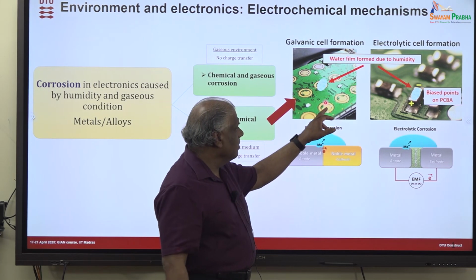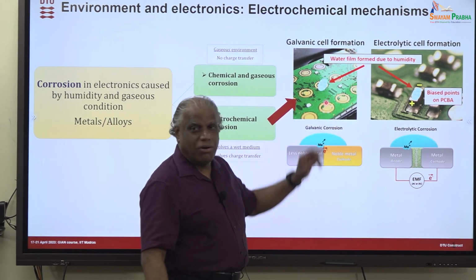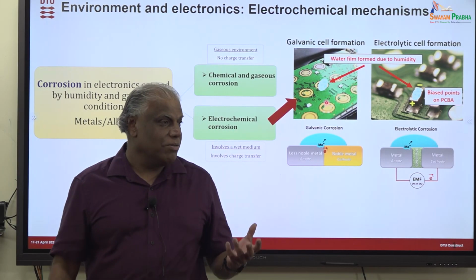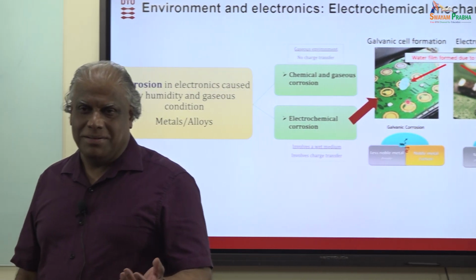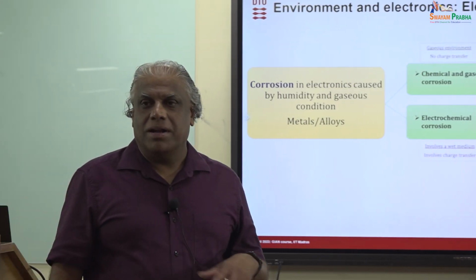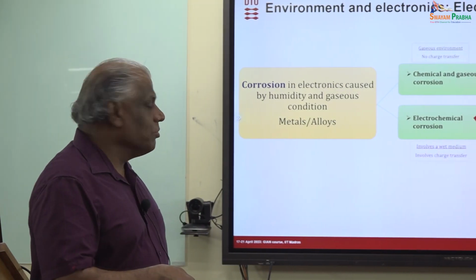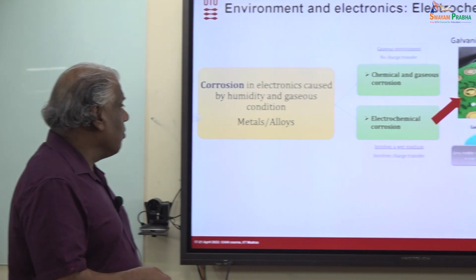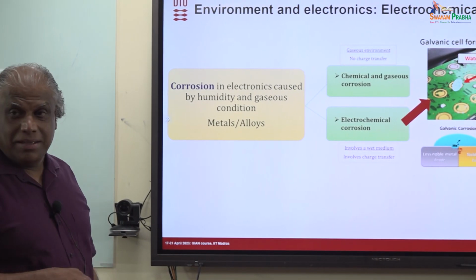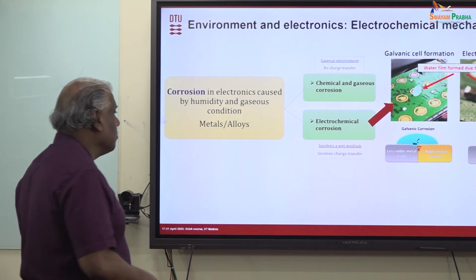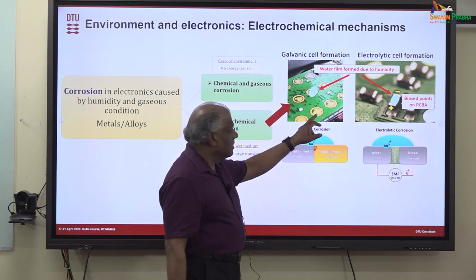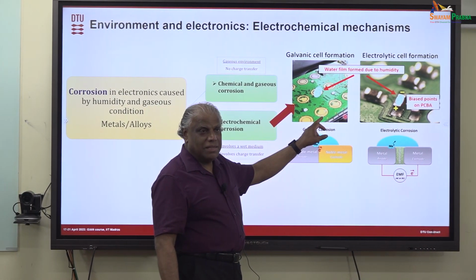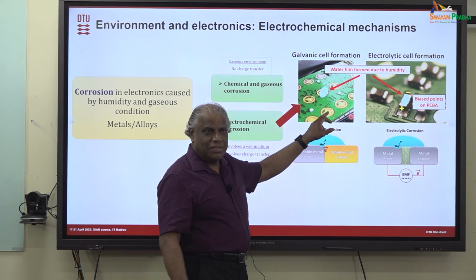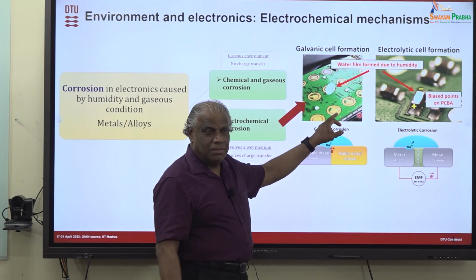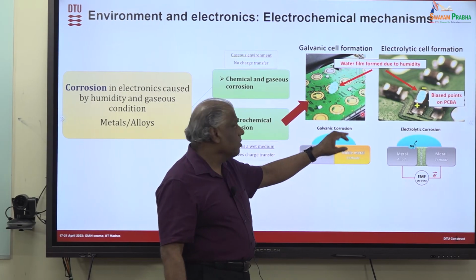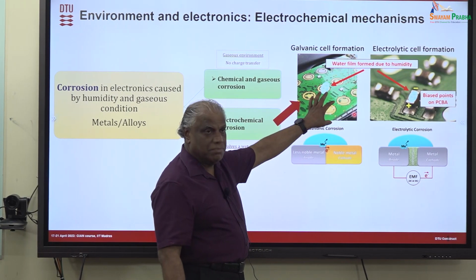Then on top of that, in order to get a good electrical contact, they put gold, because gold is a material which can give very good electrical contact, right? Because gold is a noble metal, it does not have any oxide. So for all electrical contact purposes, they use gold on the top. And this gold layer is very, very thin, because gold is very costly, so they don't want to put too much gold. This gold layer here is probably 100 nanometer thick. That means inherently, if you know electroplating, that gold layer will be very porous. So that means the electroless nickel will be exposed. In such places you can have the galvanic corrosion problem.